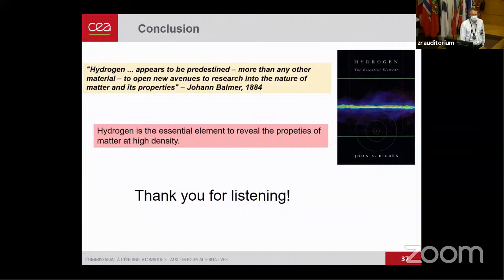Yes. So you mentioned the transition to the metal phase of hydrogen, that there have been some remarks on the fact that you haven't been able to reach a measurement of the gap. You have been able to measure a gap down to 0.1 eV. But my question is, I see clearly that you measure a very sharp transition. It's fully reversible, so clearly there is a phase transition. And I was wondering, if one wants to play devil's advocate, if there is any hypothesis about a possible alternative state that is not exactly a metallic phase, and if there are any theoretical studies that have predicted such an alternative state.